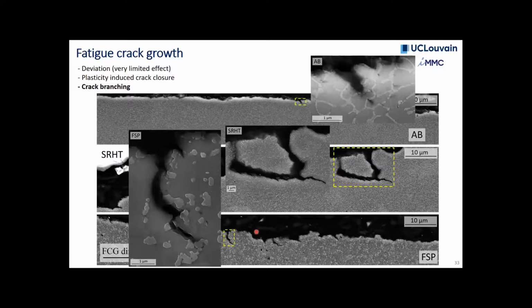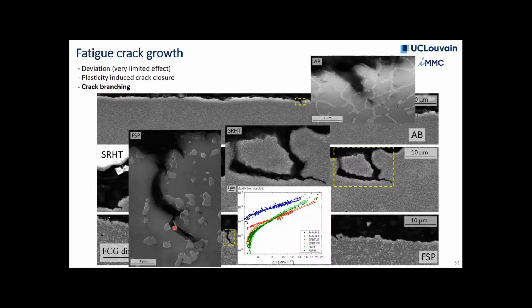And if you're zooming a bit on these locations here, this can also be associated to the difference in the damage mechanism that we have already seen in my previous explanations about damage conditions. So definitely, we can explain the lower fatigue crack growth in the stress relief and FSP materials based on maybe a bit of plasticity-induced crack closure, but mostly crack branching. So the deviations that I've shown you at the beginning is only a minor effect here.